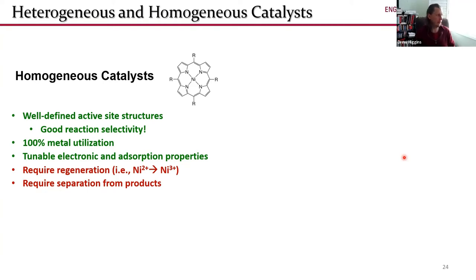One of the downsides of homogeneous catalysis or molecular catalysis is oftentimes they require regeneration. So say, for example, the active transition metal ion is nickel 2+. Once it does whatever the reaction is we're looking at, oftentimes that nickel 2+ is converted into nickel 3+. And then we need to go ahead and regenerate that nickel 3+ back into nickel 2+. So we often have to have an electrode in that solution where the catalyst will adsorb onto the electrode, regenerate back to that nickel 2+ state, and then go back into the solution, do its catalysis again, and then rinse and repeat.